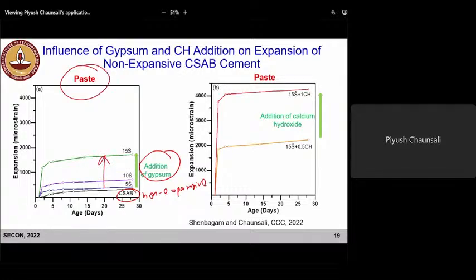Now with this 15% gypsum already present, a further increase in expansion can be observed when we add calcium hydroxide. So in this study, what we showed is that a non-expansive cement binder can also be converted to an expansive binder. And we will see what the differences are, what basically happens.